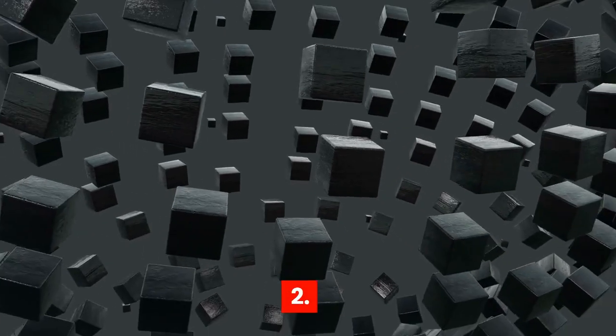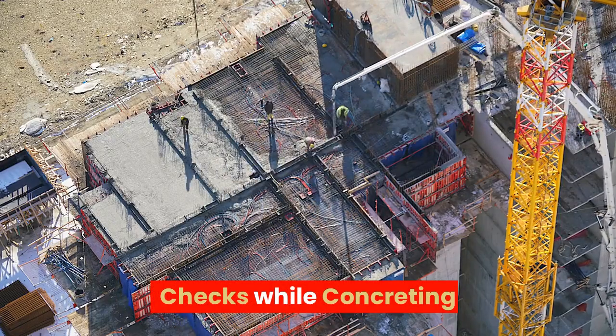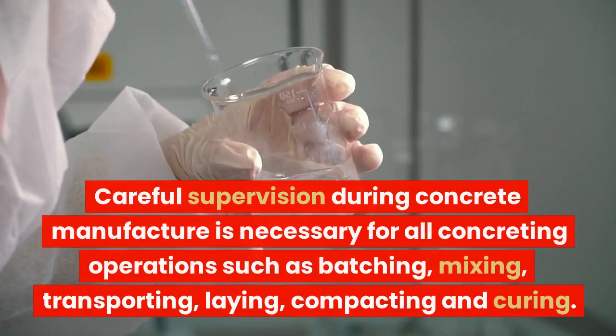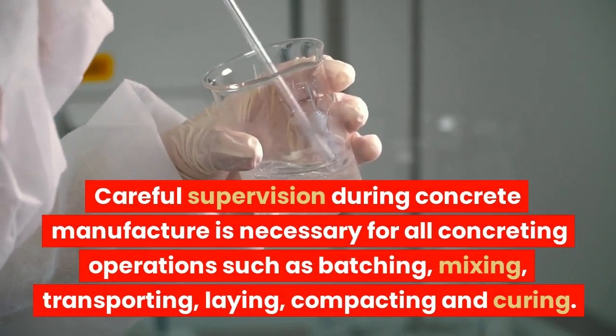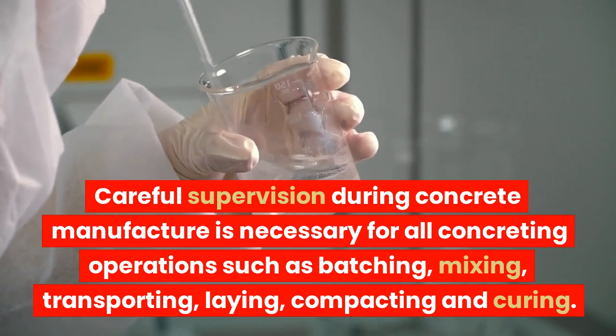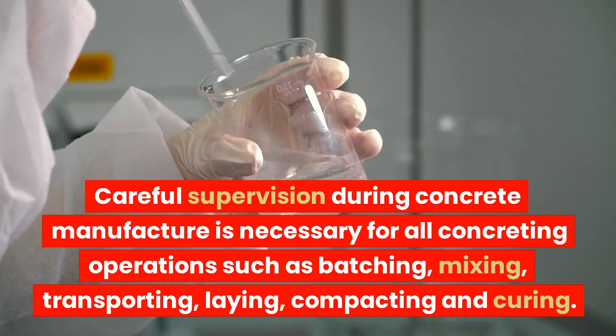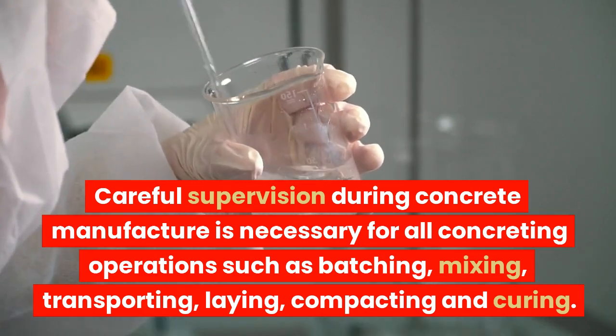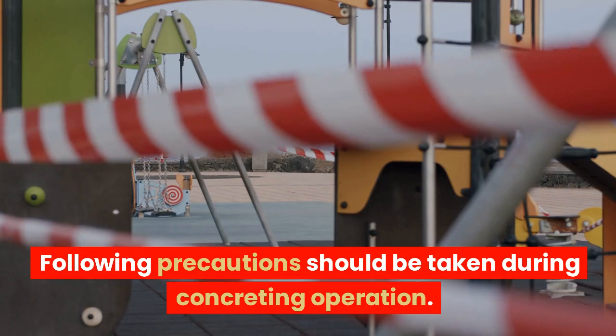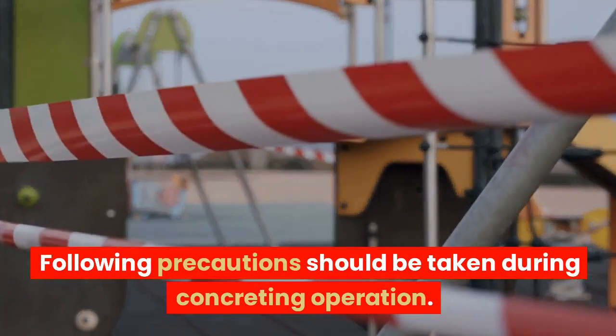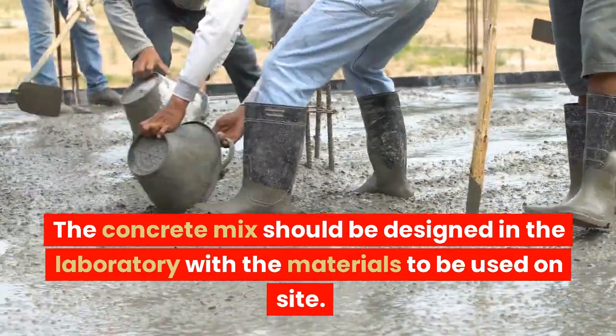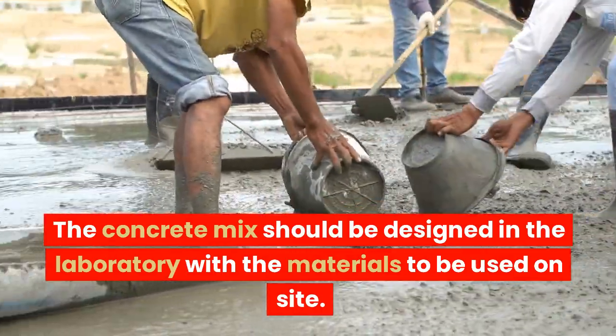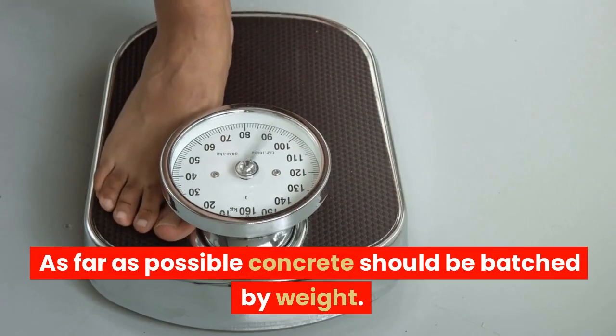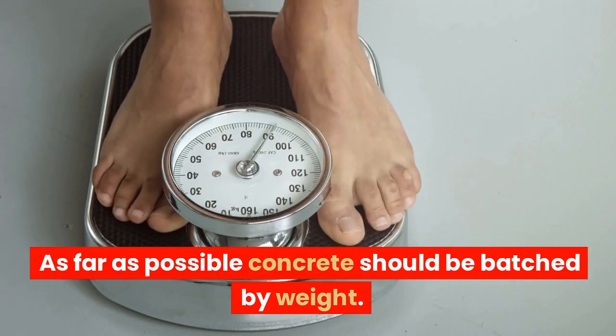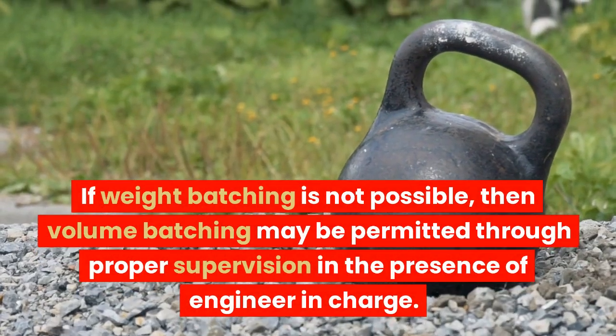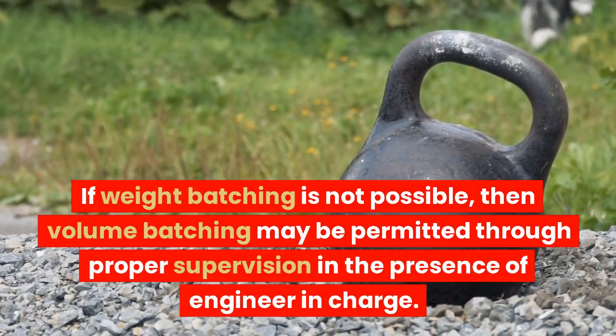Two. Checks while concreting. Careful supervision during concrete manufacture is necessary for all concreting operations such as batching, mixing, transporting, laying, compacting and curing. The following precautions should be taken during concreting operation. The concrete mix should be designed in the laboratory with the materials to be used on site. As far as possible, concrete should be batched by weight. If weight batching is not possible, then volume batching may be permitted through proper supervision in the presence of the engineer in charge.